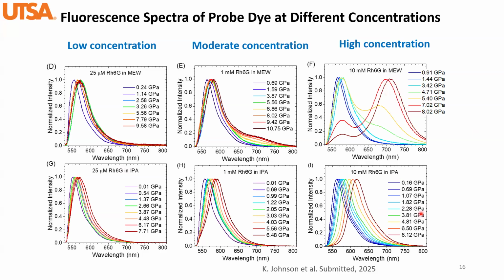In the case of IPA, it is about 20 grams per liter. And in the case of methanol, ethanol, water, it is about 300 grams per liter. If you consider the absorption, that is similar to the monomer in IPA, but the emission is significantly redshifted, and it is similar to aggregates. So by combining this information, we believe that rhodamine 6G actually forms excimers in IPA.